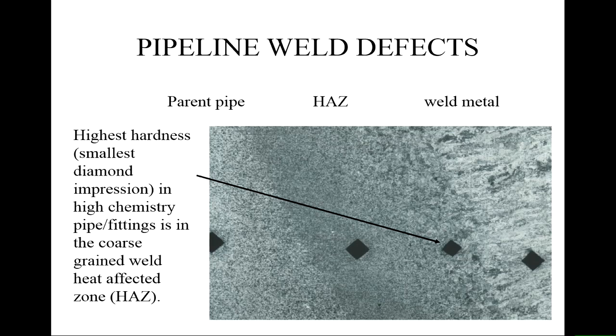Hardness is important in these cases. The harder the material, the more brittle it is. So if we put a hardness test in, this is a diamond pyramid pushed into the surface under a fixed load. The bigger this is, the softer it is. The smaller it is, the harder it is. So there's the parent metal, heat affected zone, more heat affected zone, and then the weld metal. Nice big impression, so soft weld metal, reasonably big impressions here and in this part of the heat affected zone.